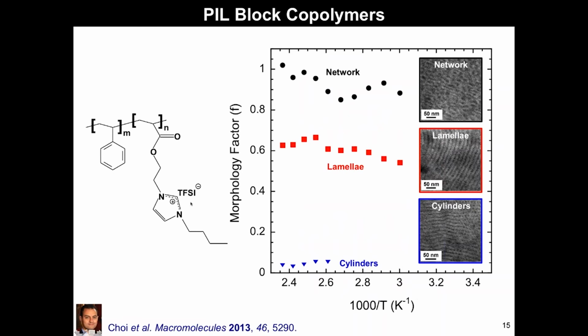Here's an example, and here's the structure on the left. This is the morphology factor, which is a normalized way of showing the conductivity, normalized by the polymerized ionic liquid homopolymer conductivity and the volume fraction. And you can see as you go from cylinders to lamellae to network, and you remove some of these dead ends and go from pseudo 2D to 3D network morphologies, you can see that normalized conductivity is increasing. And so the morphology type can have a significant effect on the ion conductivity.